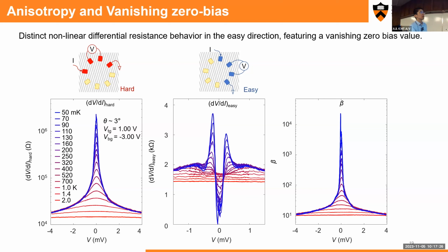And moreover, if it's a triplet, it's a completely different situation. But like most of the superconductors we have seen, we have applied up to 8 Tesla out-of-plane magnetic field, and we still couldn't see this gap behavior getting killed. So we do not favor that this state is superconductivity, but if we apply a higher field, what's going to happen, we have no idea, and we should definitely explore that.